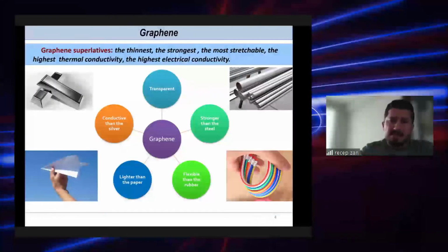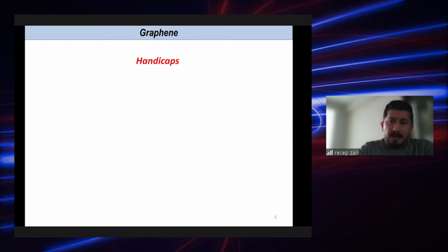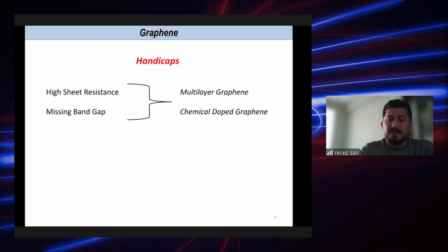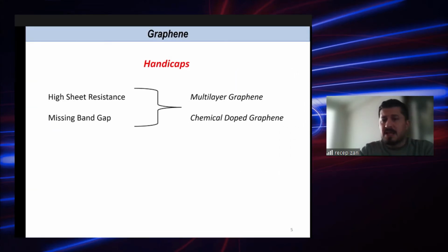Graphene is known for its superlatives: the thinnest, the strongest, the most stretchable, with the highest thermal conductivity and highest electrical conductivity. However, graphene has some handicaps, like high sheet resistance and a missing band gap. To get over these handicaps, we have two approaches so far in the literature. One is multi-layer graphene synthesis, and the second one is chemical doping.